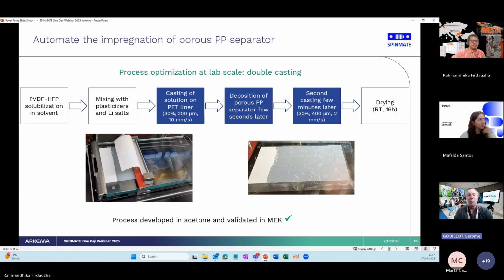The main difficulty is we have a separator with a low porosity, roughly 50%, but the pore size is quite low. So it's difficult to impregnate it, and we need a quite low viscous solution and, I would say, a low coating speed. So what we ended with was a double casting. I put some pictures, I hope you will understand.